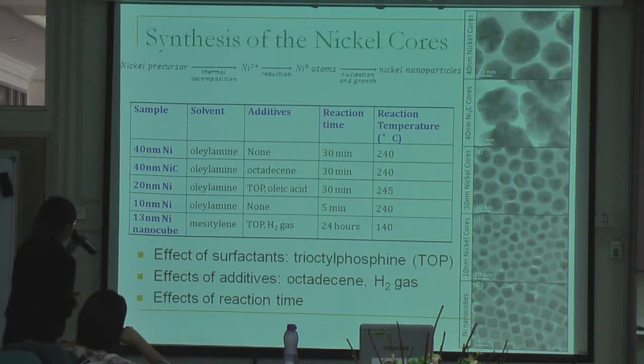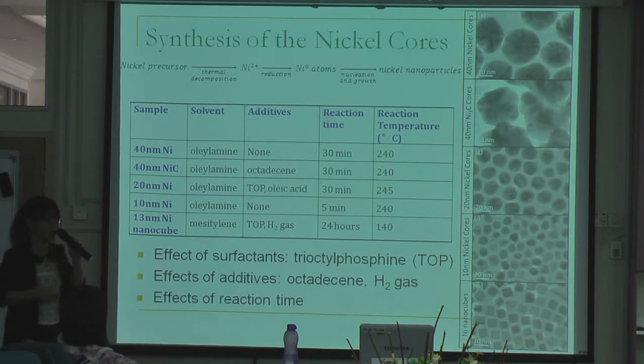In a typical reaction to prepare 40 nanometer nickel nanoparticles, nickel acetate was dissolved in oleylamine and heated at 240 degrees for about 30 minutes. When we add a small amount of octadecene, we get nickel carbide instead. That's because octadecene can react with nickel to form nickel carbide.